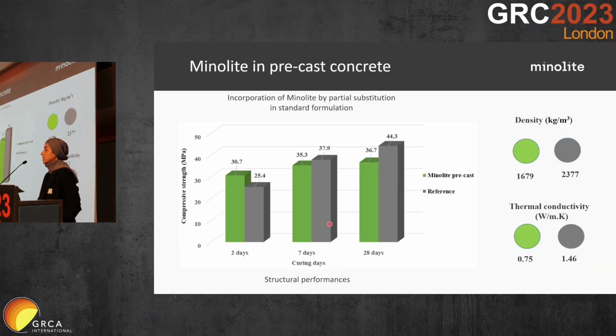Here are some of the results that I would like to show you. The compressive strength versus curing days. Minolite was used in concrete, and gravel in concrete was replaced by Minolite partially. You can see the green columns are Minolite, and the gray one is the reference without Minolite, the normal one. As we expected, the compressive strength is a bit lower, not very significant.